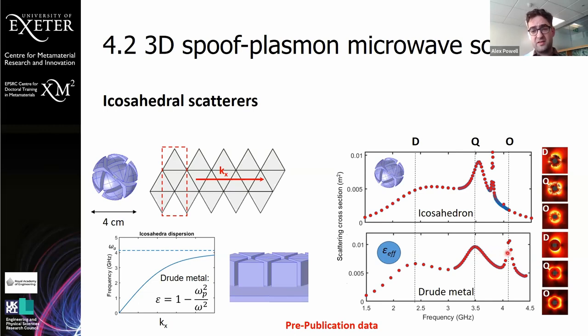And then as we get to higher orders, it starts to be a much poorer match, which, looking at this structure, makes sense, because you can see how it could easily support dipoles, and can quite well support quadrupoles, but then having an octopole with six points around an edge, your structure becomes quite large at that scale. So it makes sense that this third mode is not so reliable, but for the first two modes, I think we can say this is pretty convincingly a surface wave behavior.